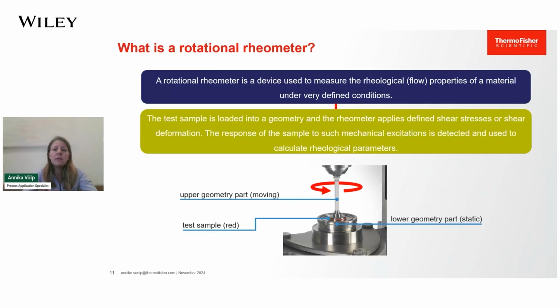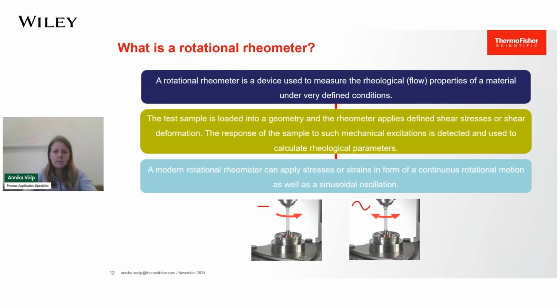A rotational rheometer usually works in the following way. The sample is filled into a measuring geometry and the rheometer applies a defined shear stress or shear deformation. The response of the sample to such mechanical excitation is detected and used to calculate rheological parameters. A modern rotational rheometer can apply shear stresses or shear strains in form of a continuous rotational motion as well as a sinusoidal oscillation. Measurements in oscillation mode are usually used to obtain detailed information about viscoelastic properties of the material.